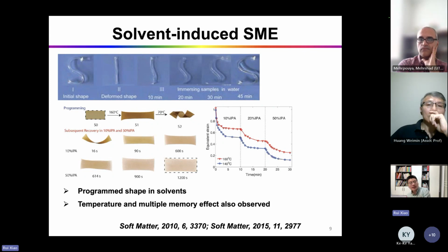You can also have solvent-responsive SMPs. That is, you put a programmed SMP in solvent, and it will recover. The reason is the solvent goes into the polymer and softens the segments and induces the shape memory effect.